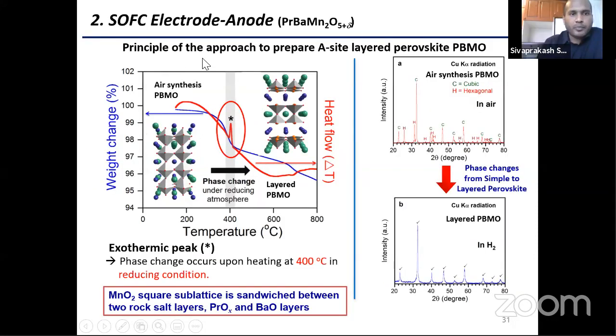Here I show how I prepare the layered perovskite material. First, I prepared praseodymium barium manganese simple perovskite material. When this simple perovskite material is kept under reducing conditions at 400 degrees Celsius, it undergoes a spontaneous phase transition from simple perovskite to layered perovskite structure. Here are the XRD peaks of the simple perovskite material, and this is the XRD of the layered perovskite material.